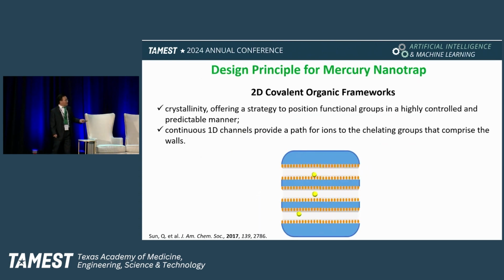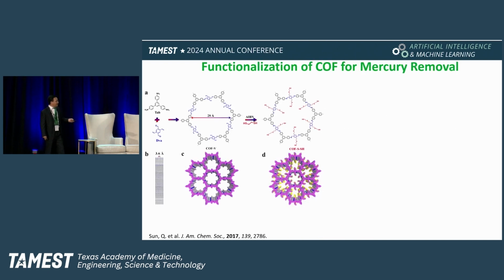One design property is that we want to make ordered materials with a lot of functional groups in the pores, so all the mercury can easily access and be captured by our material. We were also inspired by metalloproteins. They're very flexible and can cooperate intermolecularly to chelate the mercury. So this is what we designed. We use simple soft-to-soft interaction, incorporating thiol and thioether groups into our material. They can have intermolecular cooperation.